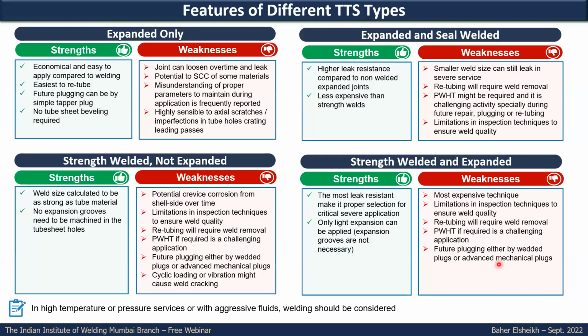very challenging exercise. In high temperature services, usually, or aggressive load, usually you cannot rely only on expansion. You need to have welding, whether you can apply strength weld plus seal plus light expansion, or expanded plus seal weld.